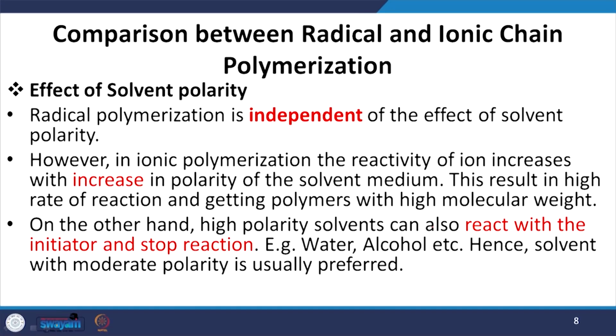Now, when reactivity increases with the increase in the polarity of the solvent, this results in a high rate of reaction and polymers with higher molecular weight. So, this is a very important thing while deciding which polymerization scheme you would like to use. On the other hand, a high polarity solvent can also react with the initiator, and sometimes it may stop the reaction. So, that is why this is very important while deciding.